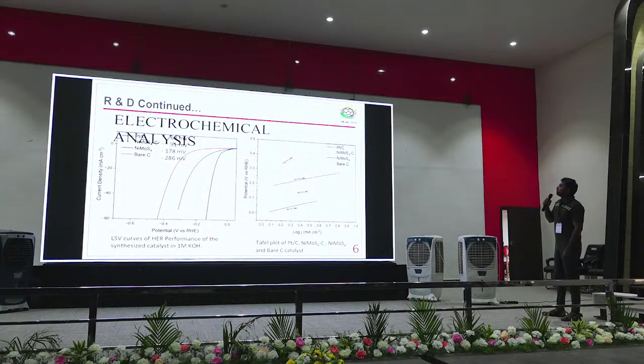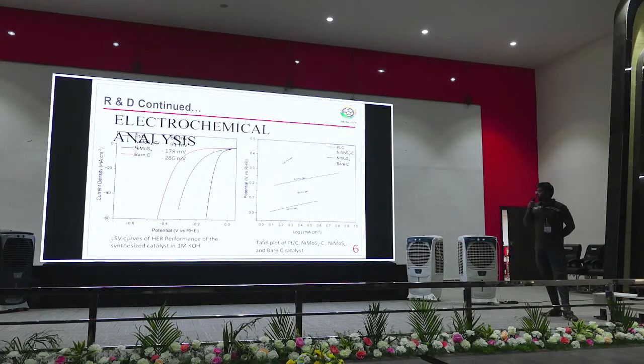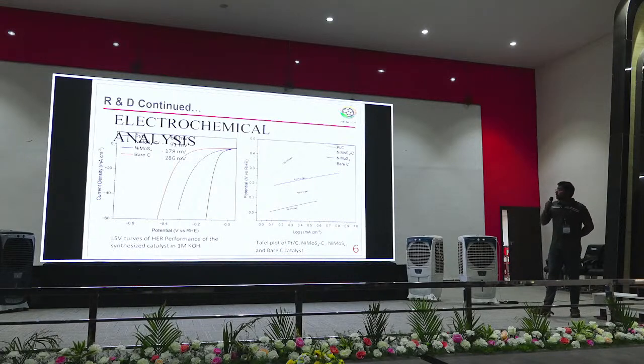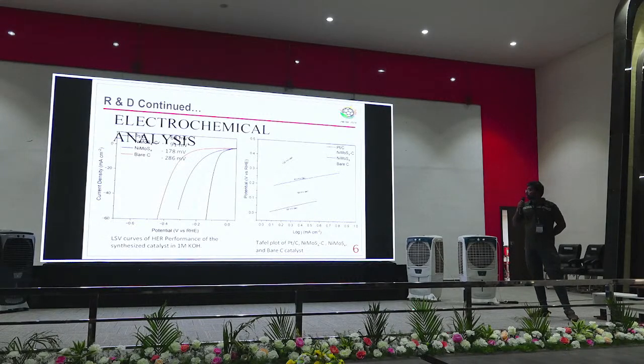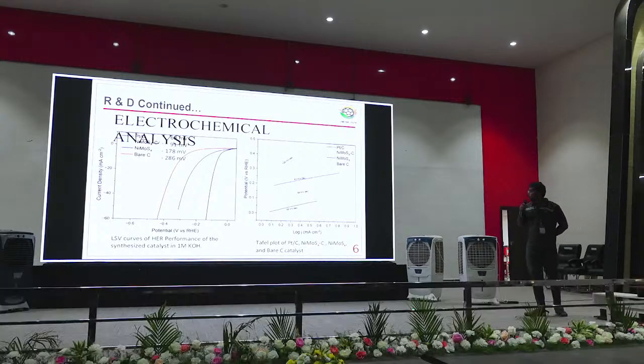The electrochemical analysis. LSV curve of HER performance of the synthesized catalyst nickel molybdenum sulfide with carbon in presence of 1 molar KOH. Platinum carbon is the benchmark catalyst, so it is compared with platinum carbon. Platinum carbon overpotential occurred at 68 millivolt, whereas nickel molybdenum sulfide with carbon was 91 millivolt. Nickel molybdenum sulfide was 178, whereas bare carbon sphere was 286 millivolt. For the Tafel plot, platinum carbon 38 millivolt, nickel molybdenum sulfide with carbon 56 millivolt, and nickel molybdenum sulfide and bare catalyst were above.